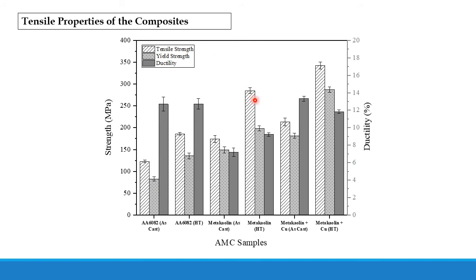The tensile property shows that the composites with metakaolin plus copper particles under as cast as well as heat treated conditions possess better properties compared to the composites with single metakaolin particles. So the ductility is the highlight fact. So it is observed that there is a considerable improvement in the ductility.